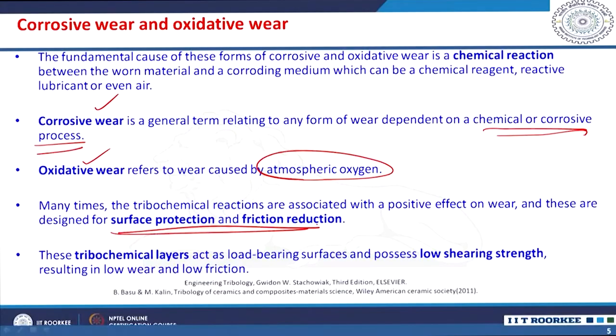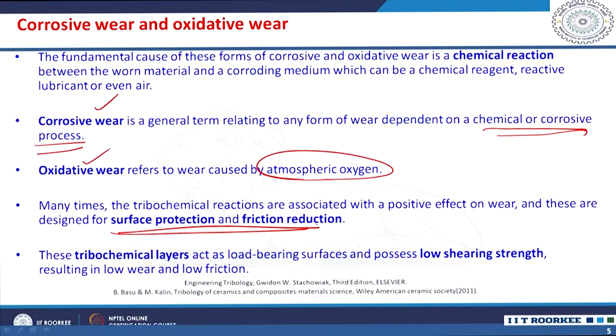Many times the tribochemical reactions are associated with a positive effect on wear, and these are designed for surface protection and friction reduction. But as I told, they can be detrimental in certain conditions as well. We will also study several example case studies where we will see the beneficial or detrimental effect of tribochemical wear for different classes of materials in different wear conditions. These tribochemical layers act as load bearing surfaces and possess low shearing strength, resulting in low friction and low wear. If the layer has less shearing strength, it will be easy to slide, so you will not have a friction increase, and the material removal can be subsequently reduced.